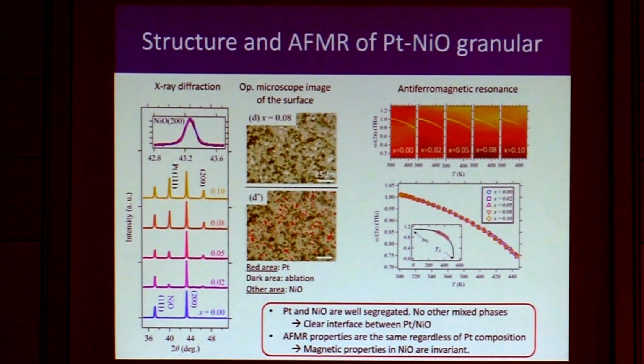First, we did a characterization of this platinum nickel oxide granular pellet. The X-ray diffraction and also the microscope images of the polished surface of this sintered nickel oxide granular sample basically tell us that there's a very clear interface between the nickel oxide and the platinum, and that nickel oxide and platinum were well segregated. We also did the antiferromagnetic resonance as a function of temperature, and regardless of the platinum composition, we see the same behavior as a function of temperature. So this tells us that the magnetic properties of nickel oxide are invariant regardless of the platinum inclusion.